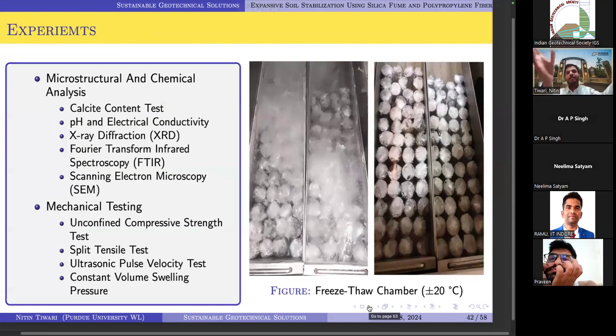Okay, so coming to the tests, again, we did the same set of tests. I'll not talk really much about it, but like calcite content, pH, electrical conductivity, XRD, FTIR, and SEM for the microstructure. When it comes to the mechanical, we did UCS, STS, and we did ultrasonic pulse velocity and constant volume, like you are seeing these tests. And these are the samples you can see in the freezing thawing chamber.